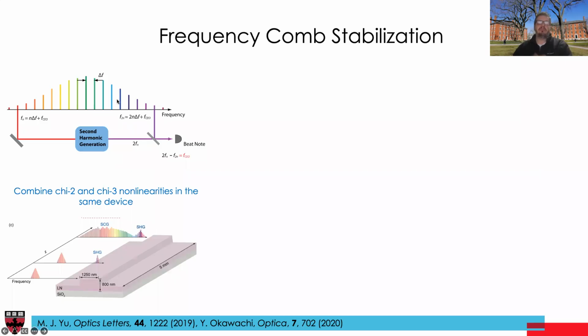Normally, when people do this, they first broaden the pulse using, as I showed in one of the opening slides, a dispersion engineered waveguide. And then after the pulse broadening, they use second harmonic generation to double the spectrum. In our case, we can do all of this in a simple lithium niobate waveguide. We hit the waveguide with the pulse, and as the pulse propagates, first we see second harmonic generation, and then as it propagates further, we see supercontinuum generation. And if the supercontinuum is broad enough to overlap with the second harmonic, by detecting this part of the spectrum, we can see the beat note, the carrier envelope offset frequency can be detected, and the whole system stabilized.